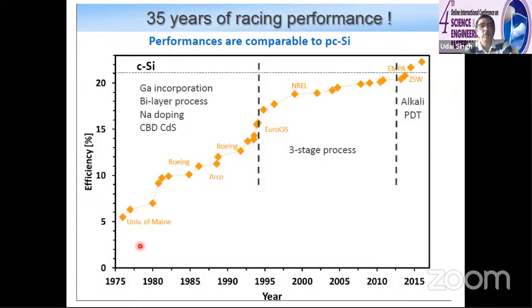So if you see the history, for crystalline silicon from 75, it's around 20, more than 20%. So not much has been changed. Only a few points, like it's 24.5, maybe 24.6, that may be the change. For CIGS, you can see the 3-stage process came in 95, so it increased to around 20%. Now post-deposition treatment of alkali metal has given the efficiency more than 23%. That was achieved in 2016, and after that, I think it's stagnant.